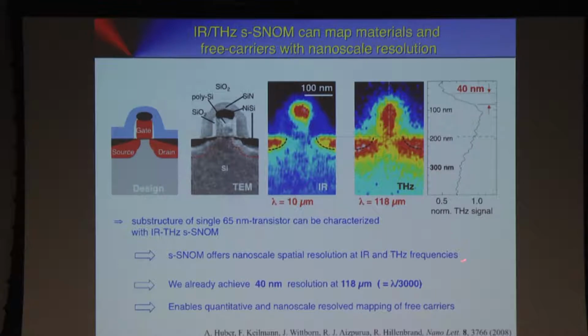So then we just switched the laser. Instead of a CO2 laser, we used a terahertz gas laser, and we imaged exactly the same device again, and we see a similar contrast here. Most impressive, if you take a line profile here, we get a resolution of about 40 nanometer. So that means we beat the diffraction limit by 3 orders of magnitude here.